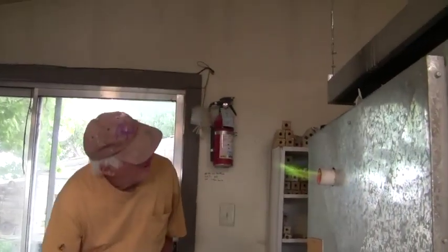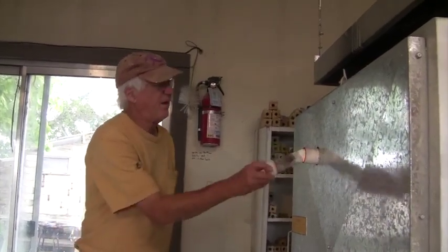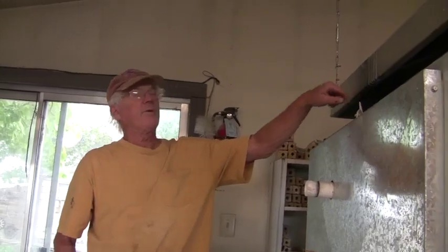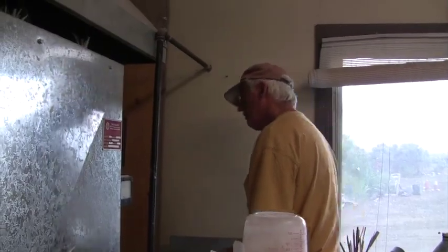But we have the cone. The cone 9 is bending like this, a little more than that. So it's not going to take another 70 minutes. If it goes 20 minutes and then I got to oxidize it again, it screws up the load. So I want to have enough time in the reduction to put the final oxidation. But our time frame is 45 minutes. It's going to be fine.